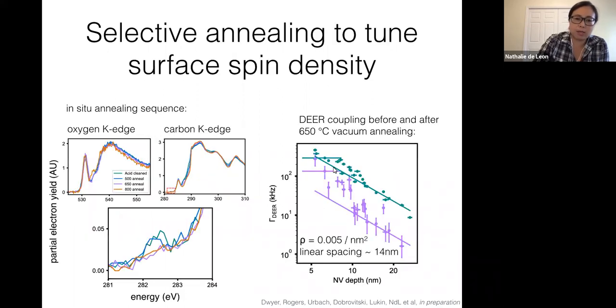So what we need is another toolkit for being able to disentangle these effects. And what we did was, at Brookhaven at NSLS, we did some in situ vacuum annealing, where we did X-ray spectroscopy after annealing at different temperatures. So we start with one of these acid clean samples, and then we anneal at 500, 650, and 800 degrees. You basically have to get to something like 800 degrees to really start pulling oxygen off of the diamond surface. But what we see is that if you zoom in on this carbon edge, after 650 degrees, this little dangling bond peak disappears. So before we've really done anything else to the diamond surface, we can selectively anneal away this dangling bond peak. And we see that after 650 degree annealing, the oxygen spectra really look basically the same.